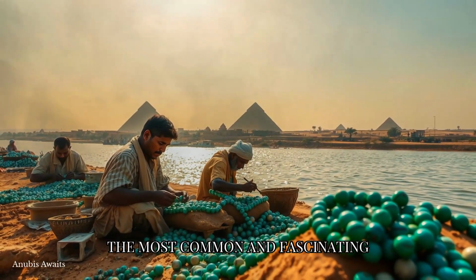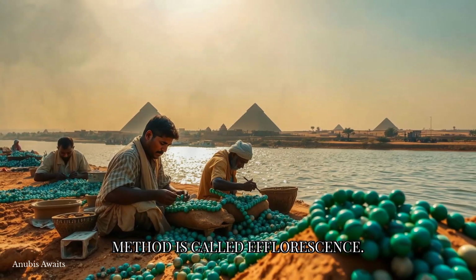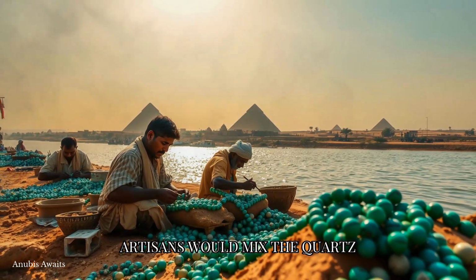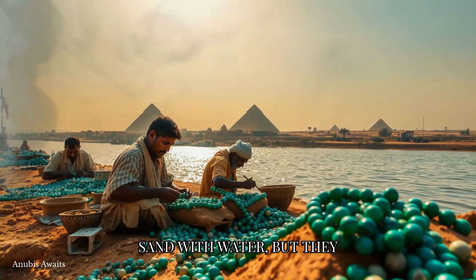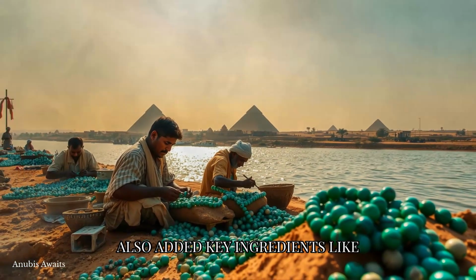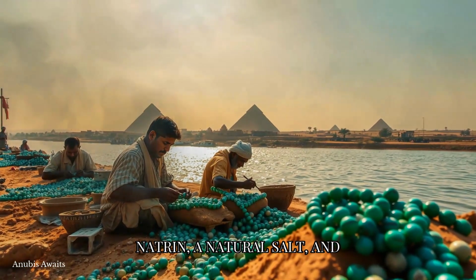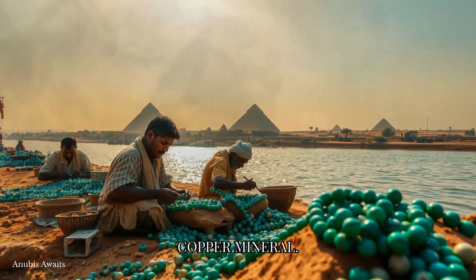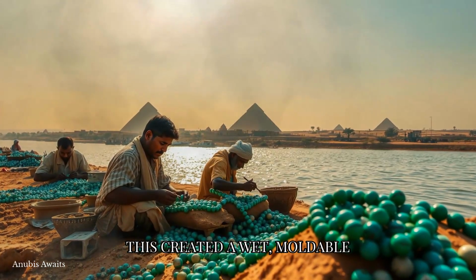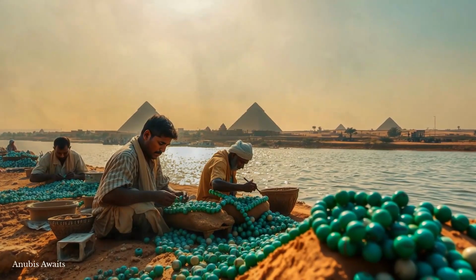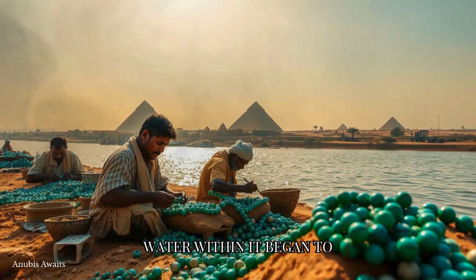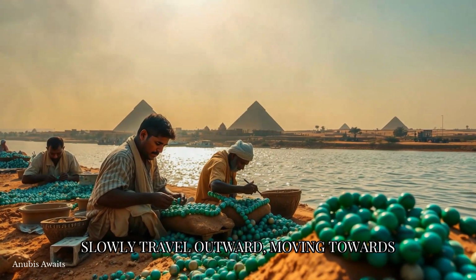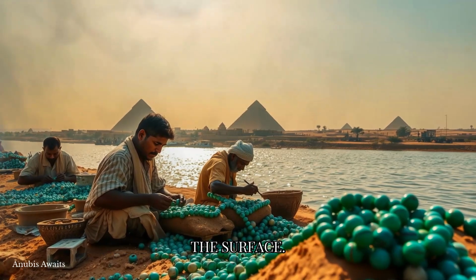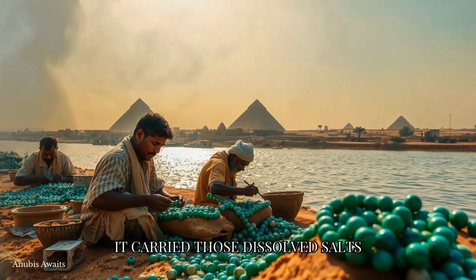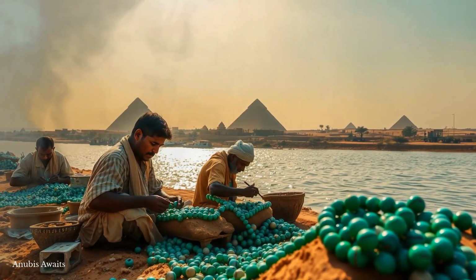The most common and fascinating method is called efflorescence. Artisans would mix the quartz sand with water, but they also added key ingredients like natron, a natural salt, and a small amount of a copper mineral. This created a wet, moldable paste. As this paste dried, the water within it began to slowly travel outward, moving towards the surface. It carried those dissolved salts and copper particles with it.